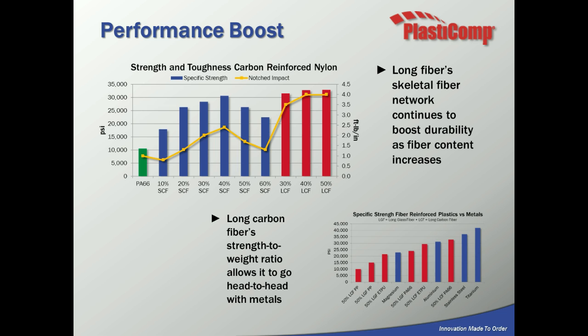If you look in the bottom right-hand corner, we're comparing long carbon fiber grades versus some common metals. And as you can see, with carbon fiber reinforced thermoplastics, we actually have higher strength than aluminum and magnesium, and we match up nicely versus stainless steel and titanium.